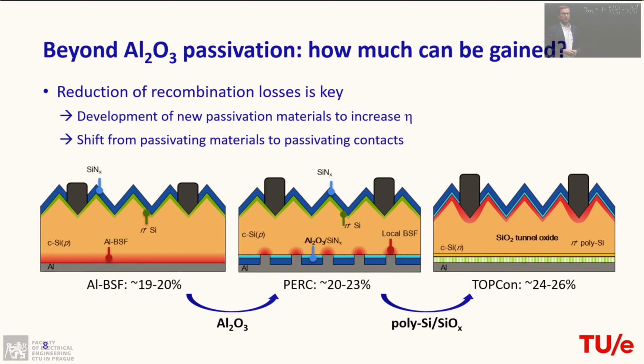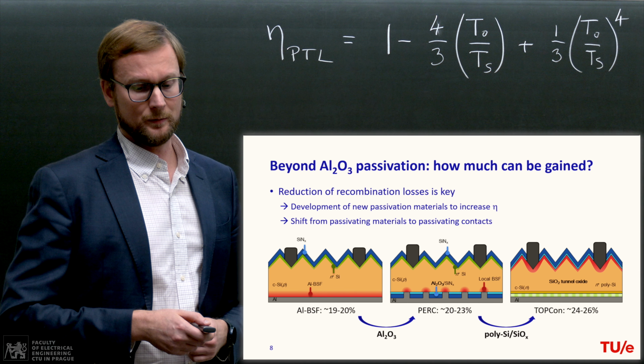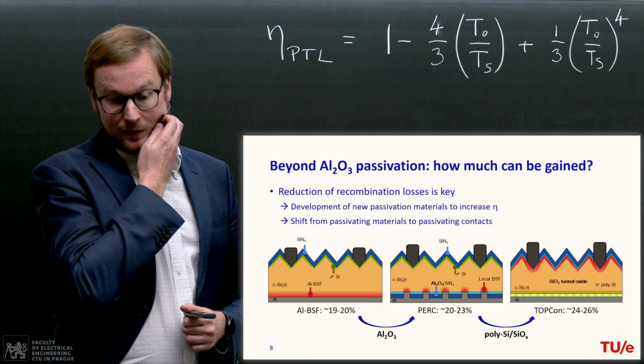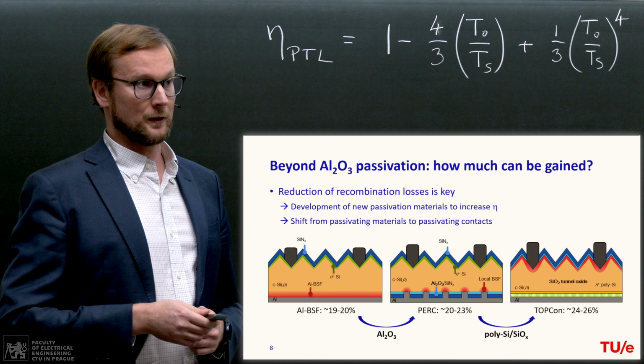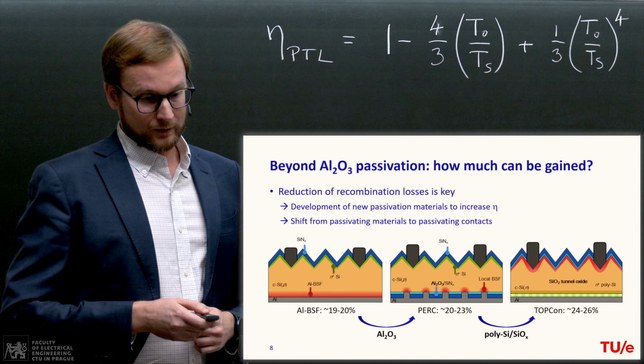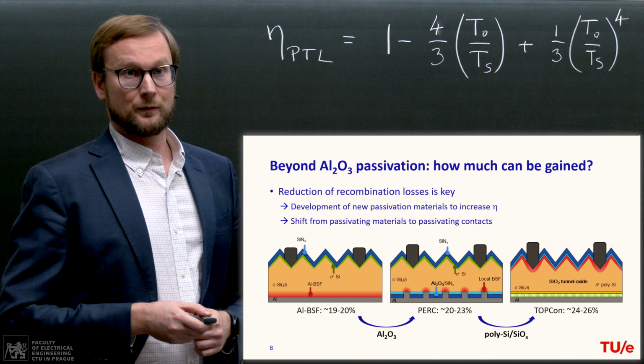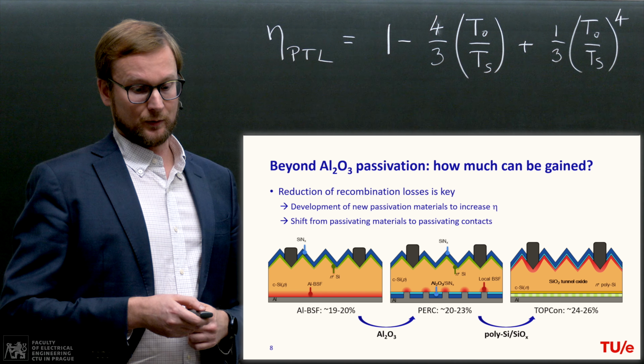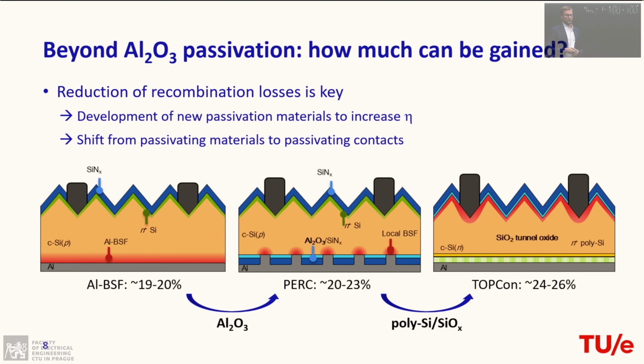Then actually, is it possible to progress still beyond this point? Of course you want to increase your efficiencies more and more. Well, the answer to this question is yes. So then you need to look for ways to reduce your recombination losses even more. That is done by looking at new passivation materials, and also shifting from this conventional structure approach with your contacts towards more passivating contacts. Because over here you basically still have metal in contact with your silicon, and that's not exactly what you want.